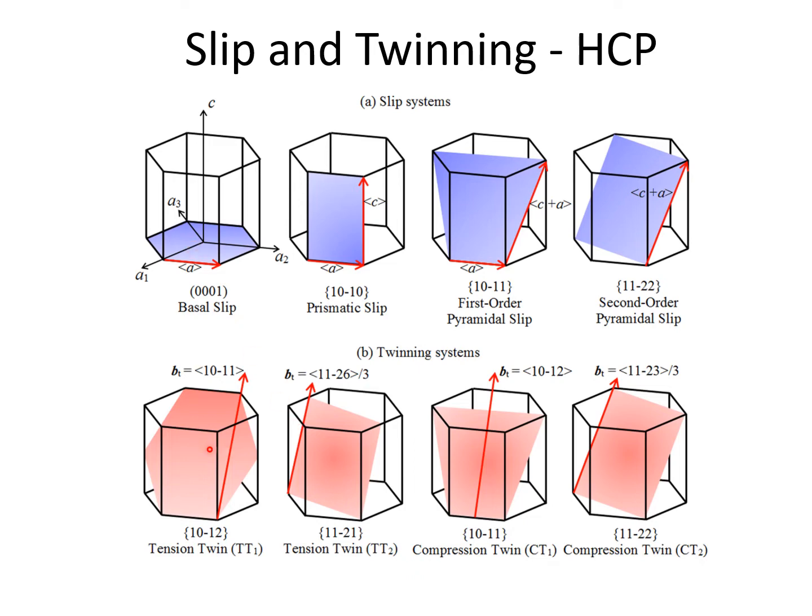There are other options for deformation, for shear deformation, which is twinning. And as I'll show you in the next couple of presentations on the video, although they won't show up in this recording, you'll have to look at them on YouTube. The stacking in the hexagonal system is not conducive to shear, twinning shear on basal planes.